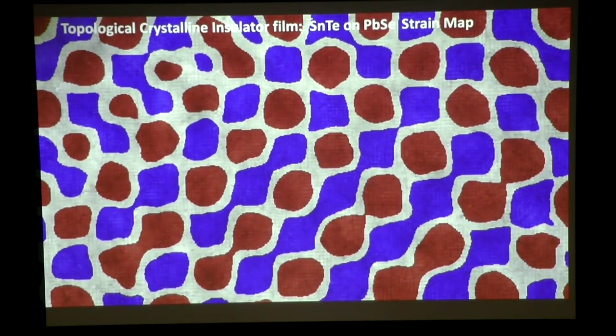This is a film that we've grown of tin telluride, which is a topological insulator, a topological crystalline insulator, on a substrate. And the lattice mismatch between these two results in this kind of superstructure. What I'm showing you in red and blue is an image of the strain in the sample. The red and blue regions show you regions of compressive and tensile strain. So we can actually measure strain at atomic length scales and correlate it with the changes in band structure also at these same length scales.